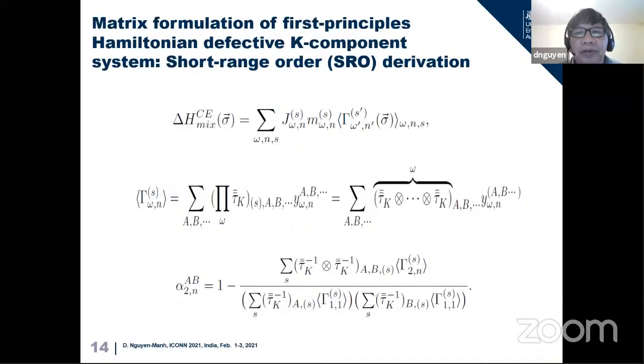So we use a first principles approach to construct the Hamiltonian. Essentially we map the interaction parameters from DFT calculation, and use these interaction parameters to do Monte Carlo simulation at high temperature. So we try to transfer from ab initio to a Hamiltonian, and then use the Hamiltonian in Monte Carlo simulation to treat the phenomena at high temperature. Essentially, I use the matrix formulation, which was recently developed mathematically.